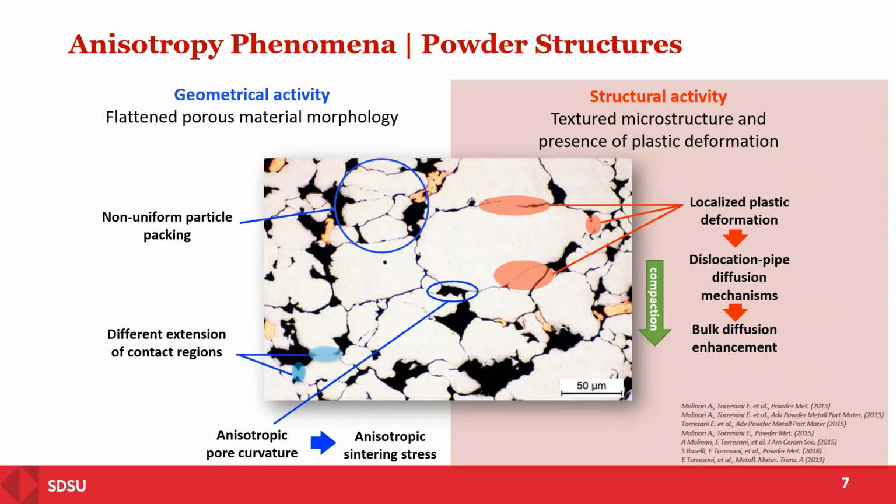So is it correct to say plastic deformation is something that happens within a grain? The contact region is just two grains touching. Yeah, they look the same in the picture, but this is plastic deformation, the irreversible strain. It happens within the grain. Yeah, so here and here, we tried to measure with different techniques the dislocations that we have, and we found differences because of the different strain that specific areas were subjected to. So it's one of the model validations that we use in this work.